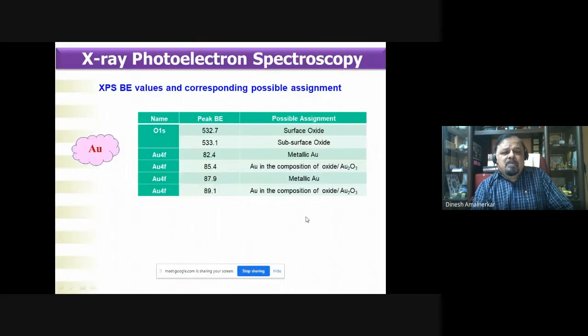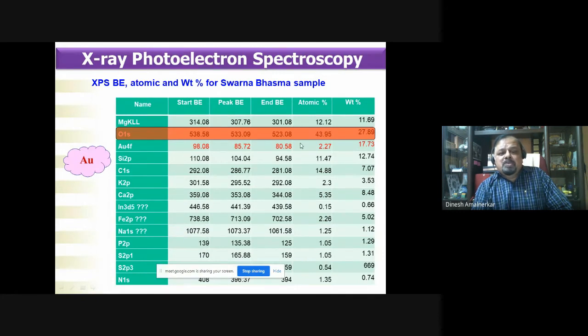So what we have done, we have seen the possible assignment in the case of Swarnabhasma. O1s indicates the presence of surface oxide with this particular binding energy value. This binding energy value indicates the presence of subsurface oxide. This value indicates metallic gold. This value indicates metallic gold. And this value and this value indicate gold in the composition of oxide, or Au2O3. Percentage wise, probably it's the same. Oxygen concentration is much higher compared to anything else, which closely matches the FESEM, EDAX, and TEM, STEM, HAADF elemental mapping data. So this is about gold.